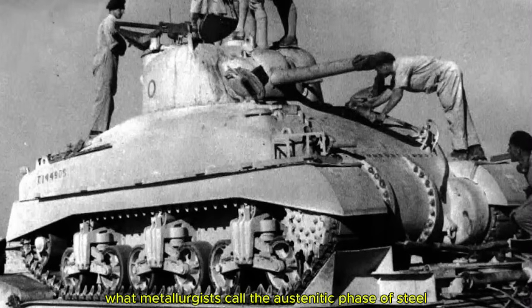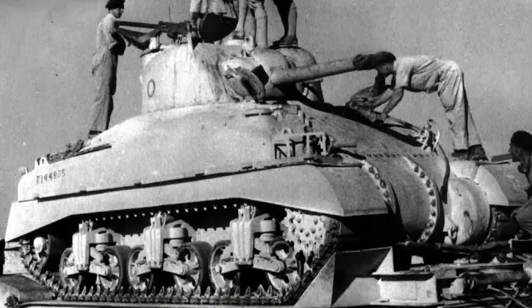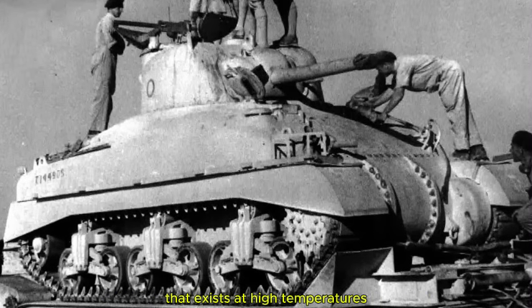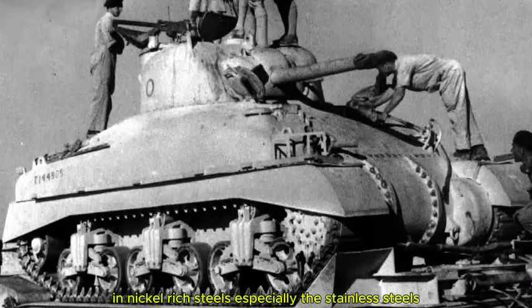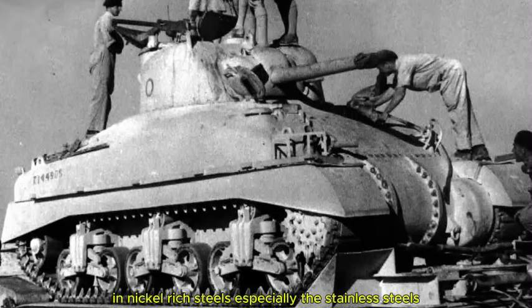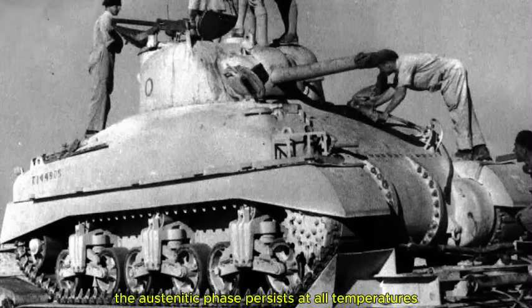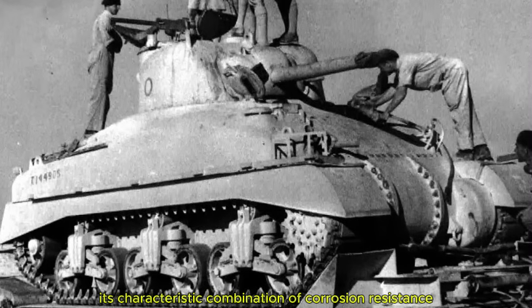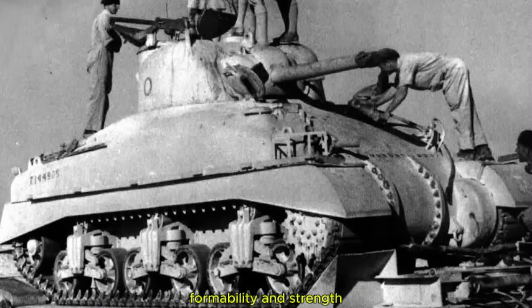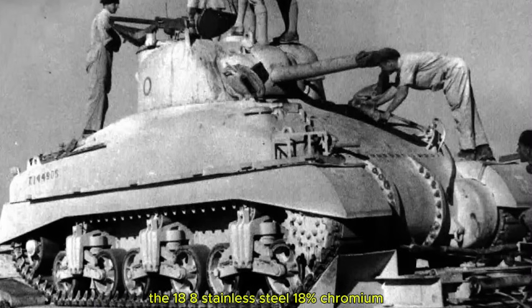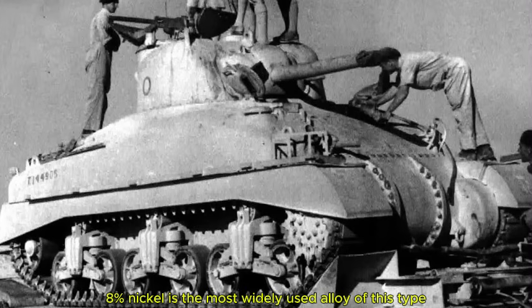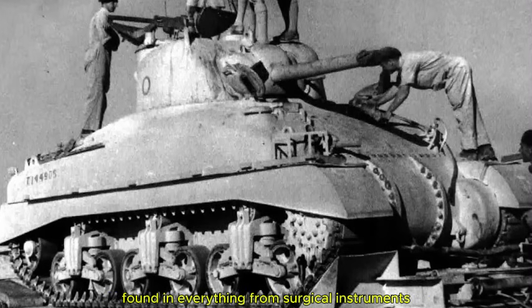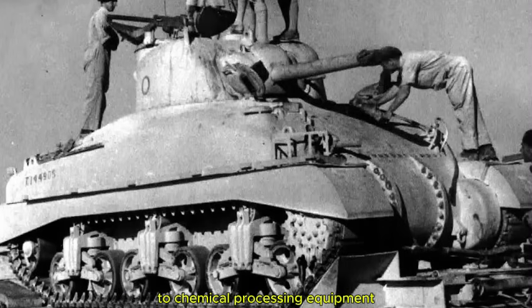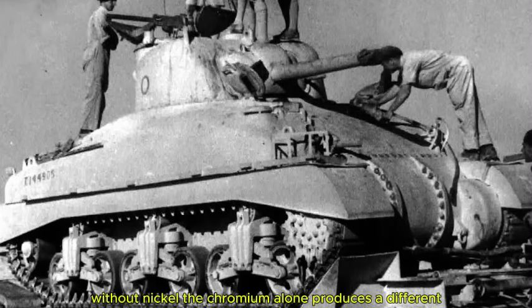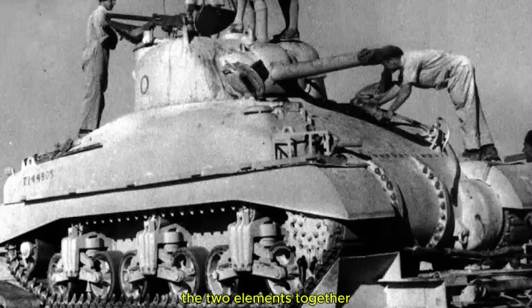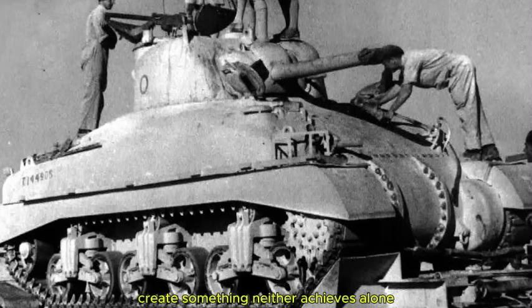Nickel also stabilizes what metallurgists call the austenitic phase of steel, a particular crystalline arrangement that exists at high temperatures and is normally unstable at room temperature. In nickel-rich steels, especially the stainless steels that also contain chromium, the austenitic phase persists at all temperatures. This gives the metal its characteristic combination of corrosion resistance, formability, and strength. The 18-8 stainless steel, 18% chromium, 8% nickel, is the most widely used alloy of this type, found in everything from surgical instruments to chemical processing equipment. Without nickel, the chromium alone produces a different, more brittle crystal structure. The two elements together create something neither achieves alone.